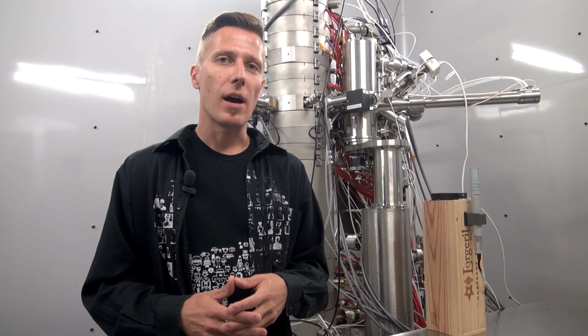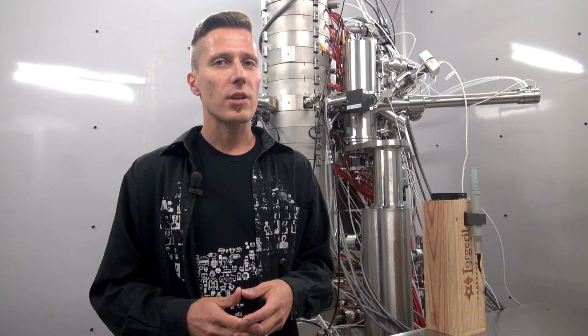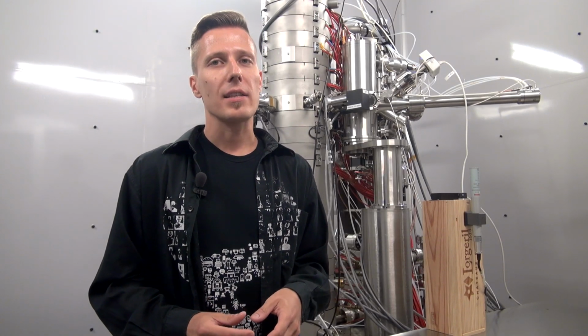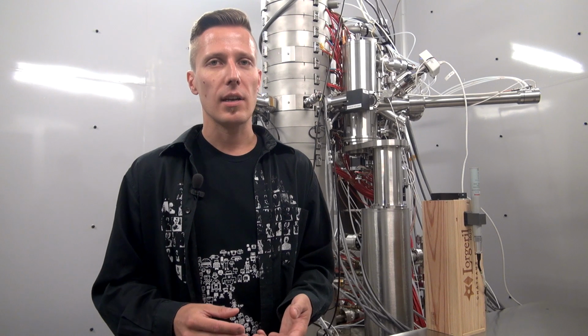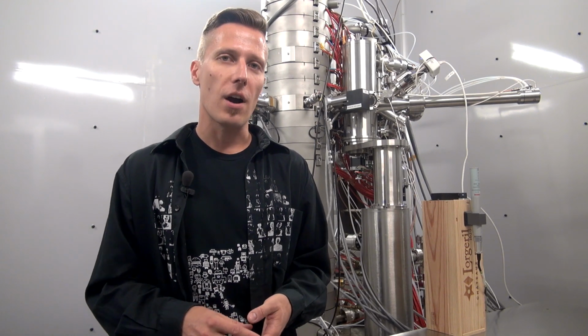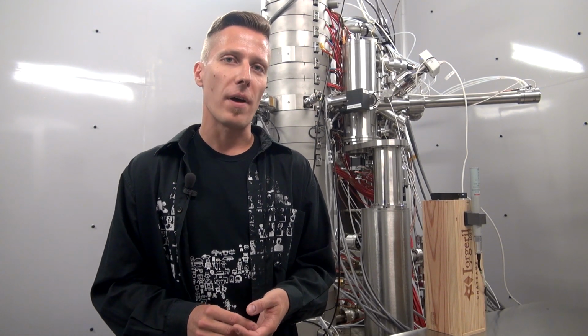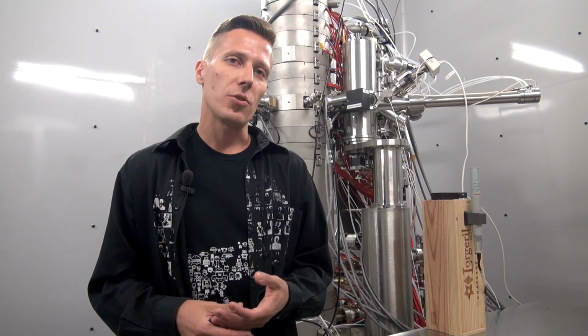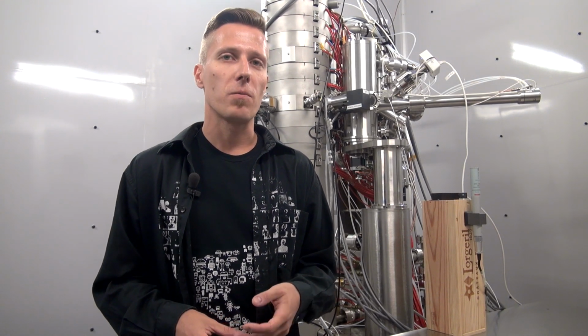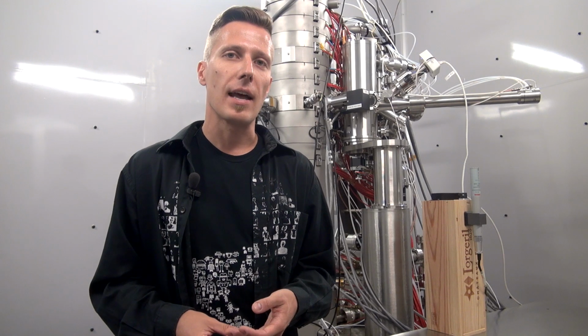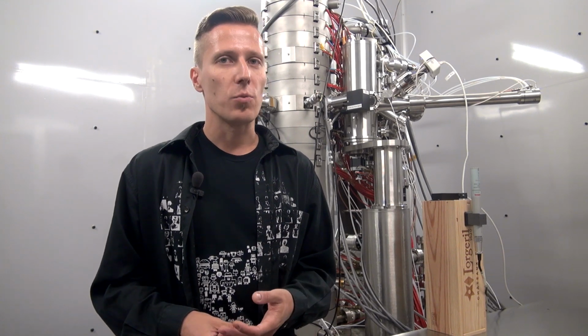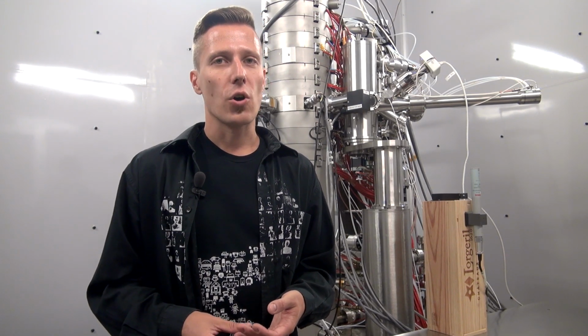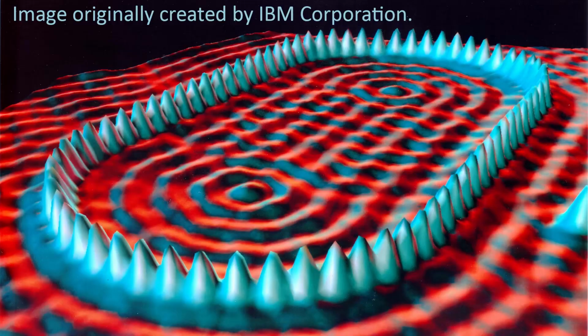Finally, although it was beyond our present scope, what makes the results truly intriguing is the fact that the bond flip is directional. The silicon moves to take the place of the carbon atom that was hit by the probe electron. This means that it should be possible to control the movement of one or more silicon atoms in the graphene lattice with atomic precision without causing any damage. So it may well be that we'll see a different kind of quantum corral or a university logo written with silicon atoms in graphene sometime in the near future.